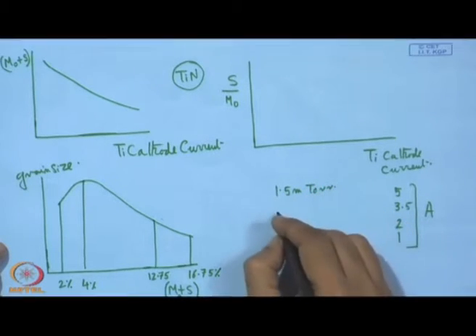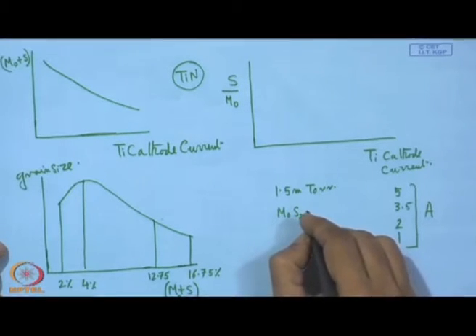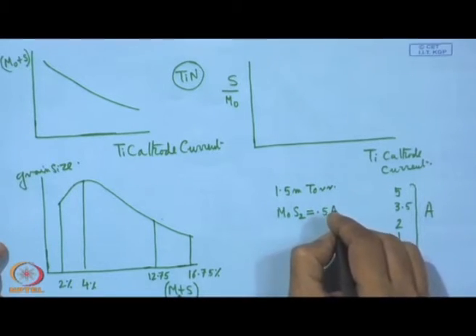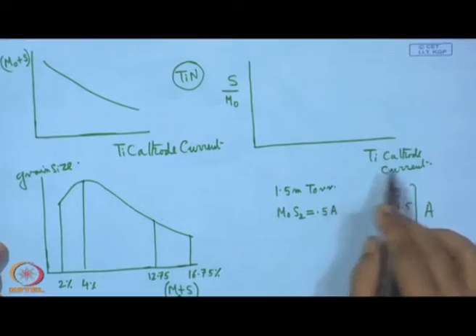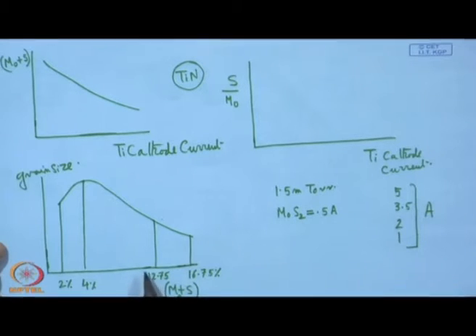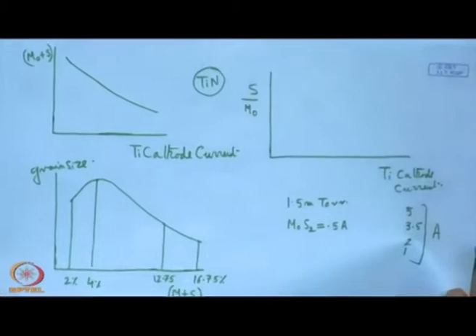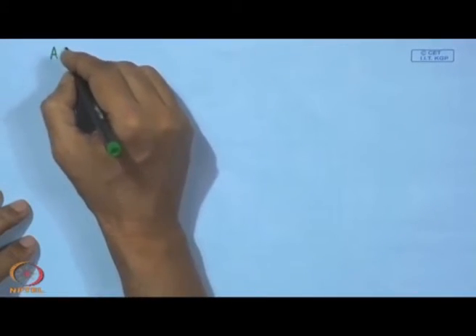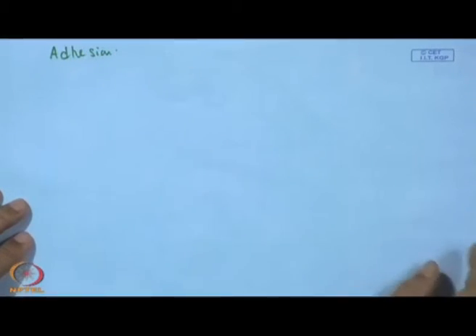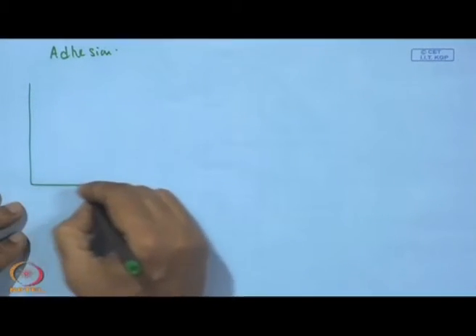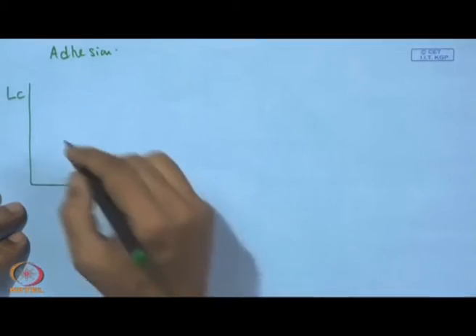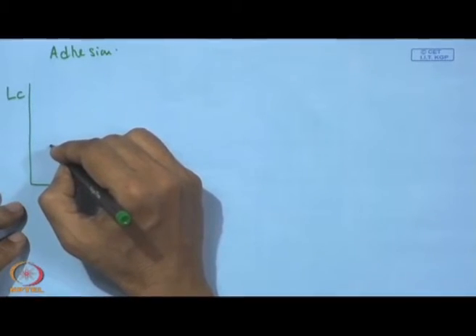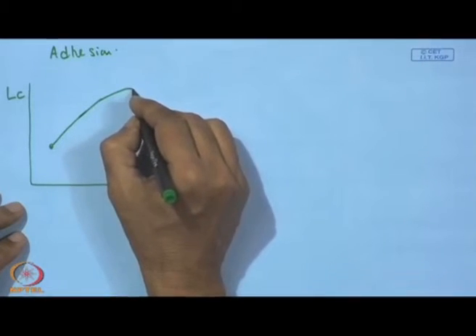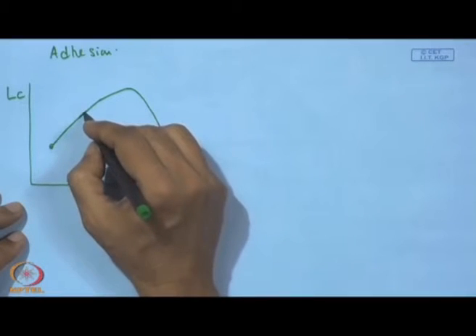millitorr, MoS2 cathode current was restricted to 0.5 ampere, and the cathode current of titanium was varied. So, with this we can get a grain size of this order, and then comes a very important thing, that is the surface, that means the adhesion. So, with this what we can see here is the LC, the critical normal load, and this critical normal load, what we found, is like a rising and a falling curve.